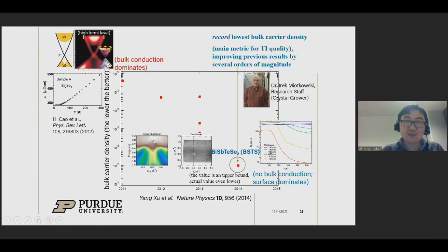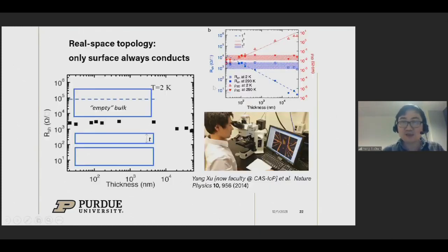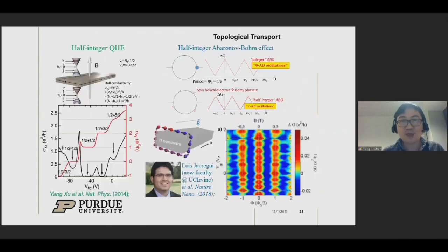Here, the band structure is dominated by, at least near the Fermi level, only the Dirac surface state intersecting, in fact very close to the Dirac point. And that's the starting point for many of our device works later. In fact, on this kind of material, when you reduce the thickness, keep cutting to different thicknesses, the sheet resistance can barely change because the bulk is empty. This geometric effect was actually very difficult to observe in the earlier generation of topological insulators, but now we can see this in these very good quality, bulk insulating topological insulators.